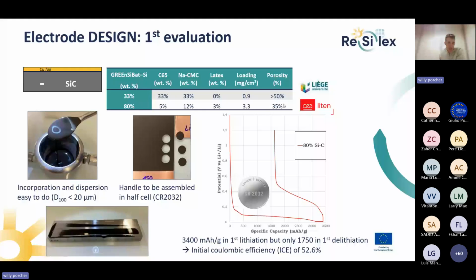We start with the slurry dispersion, and already a good point: it was a really easy incorporation and easy dispersion of the material provided by University of Liège. You can see on these gauges, which are in micrometers, that we are able to detect the biggest particles, and there were no particles bigger than 20 micrometers. And even with less than 20% of inactive components, we were able to cut these disks that we will handle afterwards to assemble the coin cells.